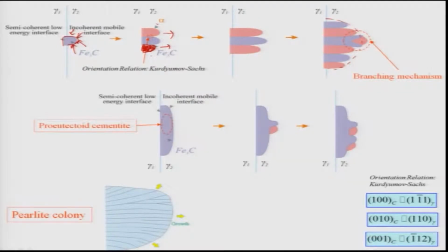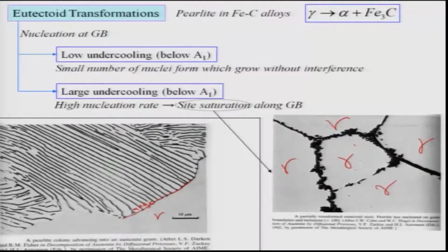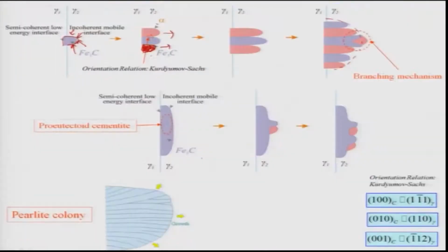Let me show one such colony, as seen in this picture. This is one colony, and this is a gamma grain. This colony is growing into the gamma grain, and this is normally observed. So I can easily explain the formation, or the growth, of these pearlitic colonies in the transformations.